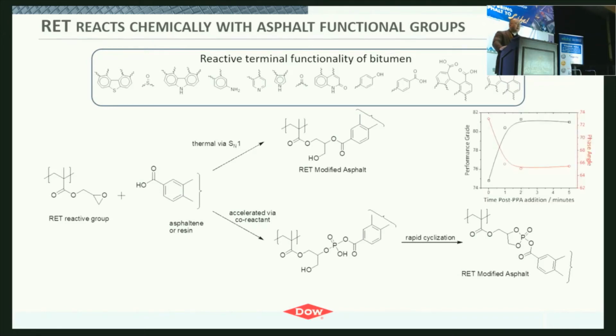In the lab, in quarter-gallon blends, after you have your polymer dissolved through low shear mixing, you add your PPA. In about 2 minutes, you can saturate your continuous grade and your phase angle.